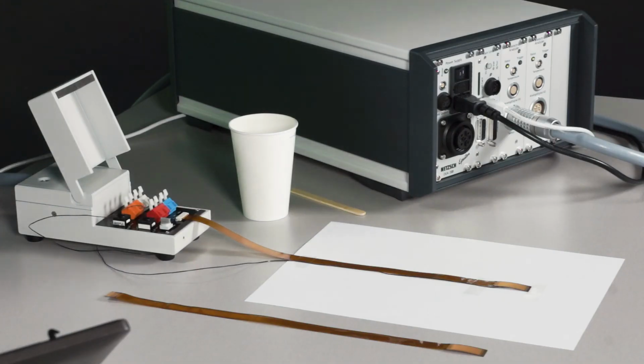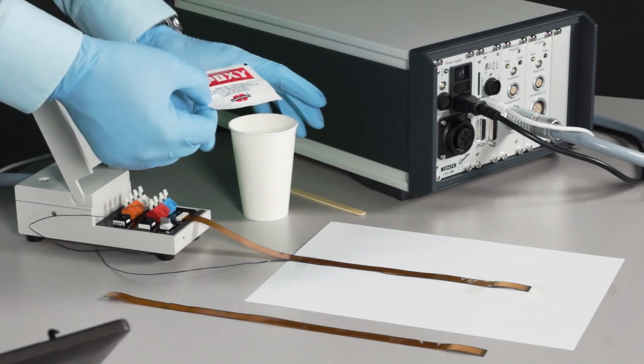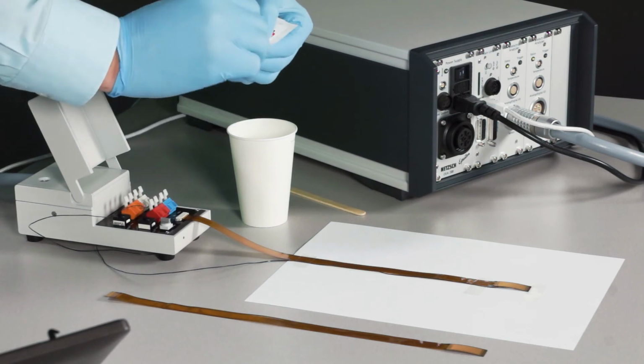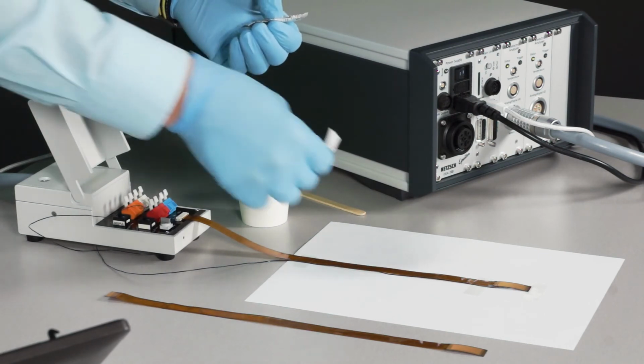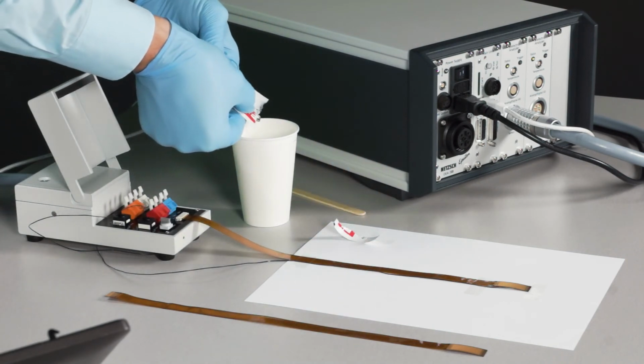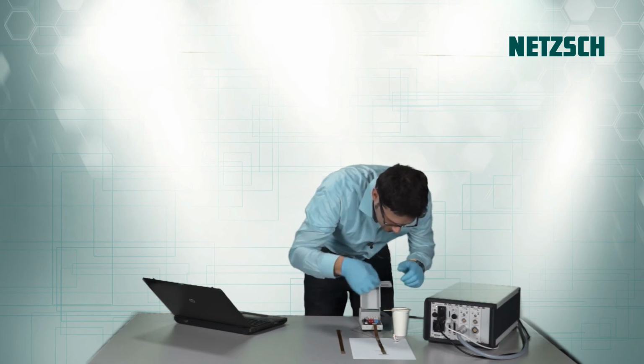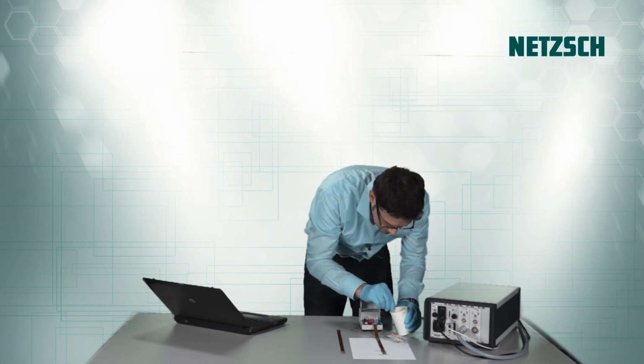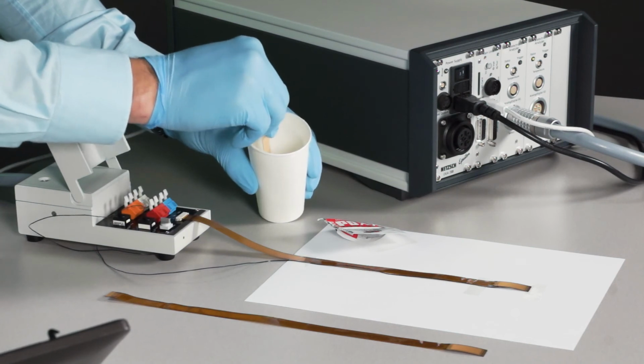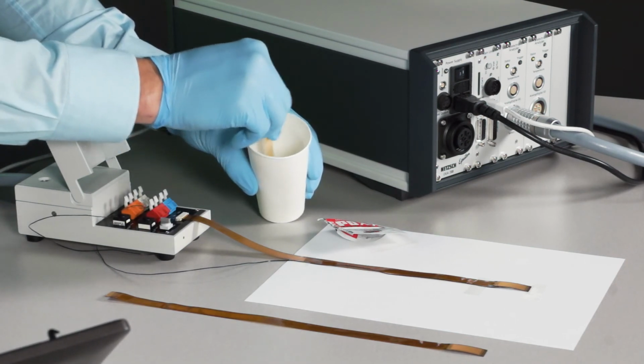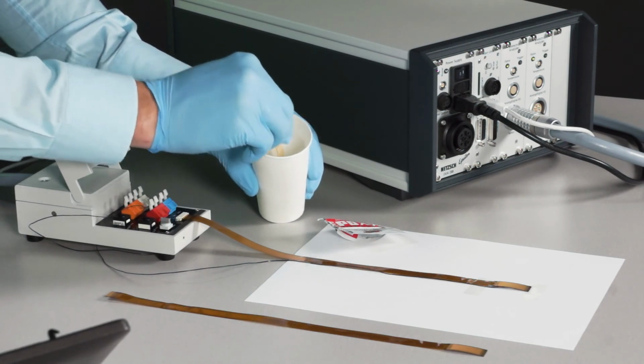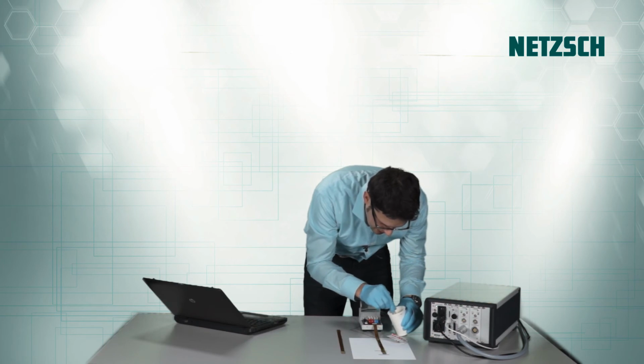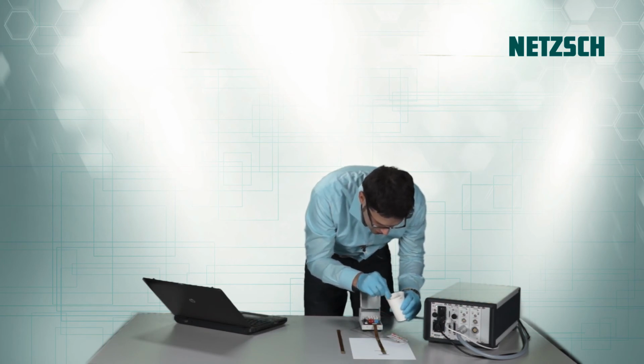Now I will open the package of the 2-component epoxy resin. I will put it into the cup and mix it. The 2 components are mixed homogeneously inside of this paper cup. You can also use an aluminium cup or something else, but it is important, as the system is curing inside of the cup, that you use a disposable cup. Mixing for 10 to 15 seconds should be sufficient to achieve a homogeneous mixture.